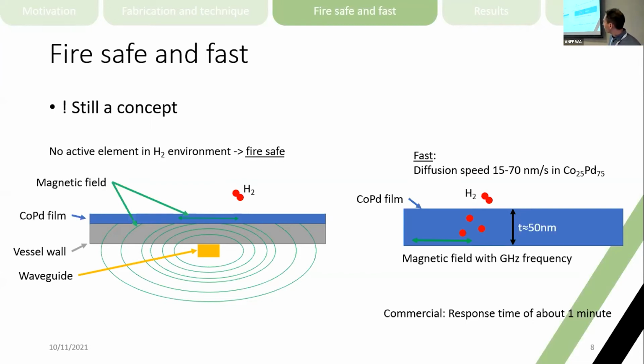However, the microwave magnetic field is completely shielded by the cobalt palladium thin film, so nothing of that microwave magnetic field actually penetrates the hydrogen vessel itself. So we can completely separate all the active elements, so the waveguide, from the hydrogen environment. That makes it very fire safe.